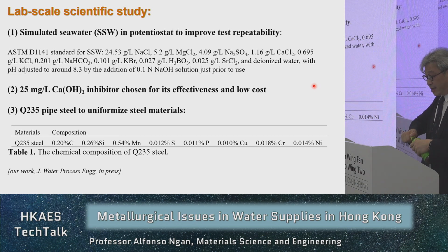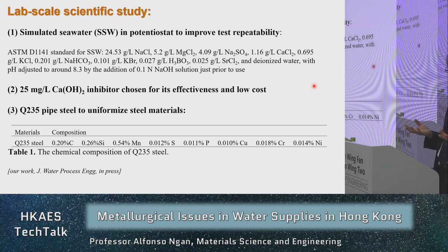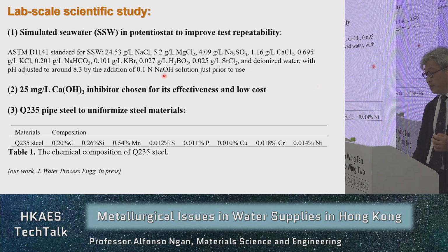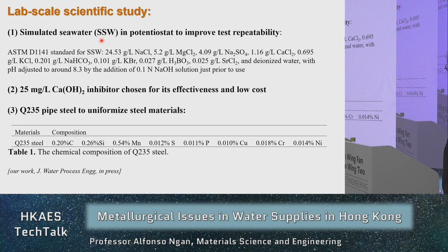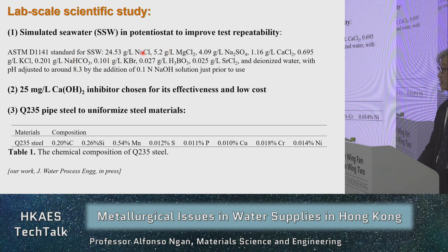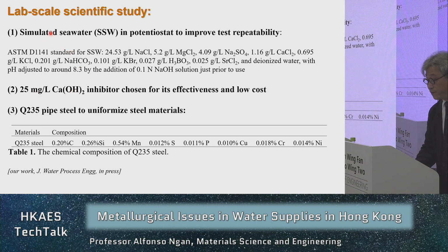But the problem with using real seawater is that real seawater pumped out from the ocean is very varying. There are a lot of variables which are hard to control, and therefore the results won't be very repeatable. So for that, we switch to simulated seawater, SSW. So there are standards around where you can mix up chemicals to form this sort of SSW, simulated seawater. Okay? And because all the conditions are fixed, at least the water itself is not a variable. So for this scientific study, we just keep the inhibitor condition to be 25 milligrams per liter of calcium hydroxide. And also we focus on just one type of steel, which is a very common pipe steel, Q235 pipe steel, with compositions listed in here.